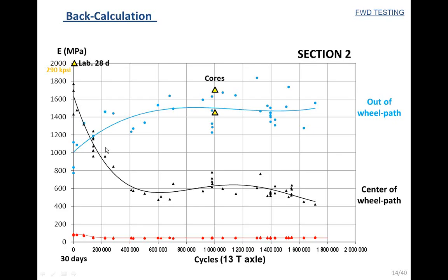When you see here the evolution due to damage, the first thing that we were surprised to see is such a fast damage. We saw that the material was decreasing the modulus very quickly under the loads. And in fact, when we were at this point of the test, around cycle 300,000, we were expecting this line to come to almost zero, or maybe to 100 megapascal. But the fact is that the modulus got stable around 500, 600 megapascal, which for us was a very high value. We were not expecting that type of performance. We were expecting maybe 100, 200 megapascal. This stabilization was a bit surprising for us.